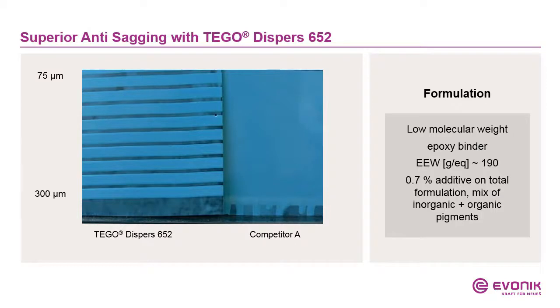The rheology is also very interesting. That can be seen with TEGO Dispers 652. It gives a certain yield point so that you will see an anti-sagging effect of the TEGO Dispers 652 when you use it in an epoxy system as wetting and dispersing additive.